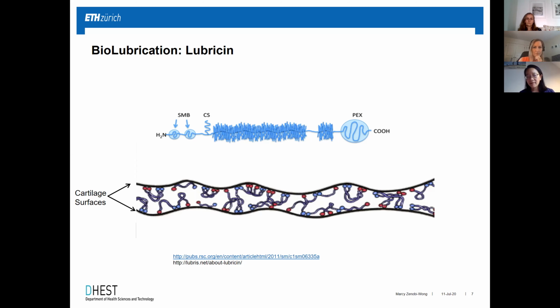And if you have no lubricin, so this can be in a mouse model where it's knocked out, you find that these animals actually get arthritis at a much higher rate. So it really plays a role in a surface being slippery. And so we're interested in what causes the cells to start expressing this molecule, and actually the shear stress is one of the factors which causes the cells to express it. But once you have lost this surface layer, once you have the early stages of arthritis, you have lost this low friction environment.